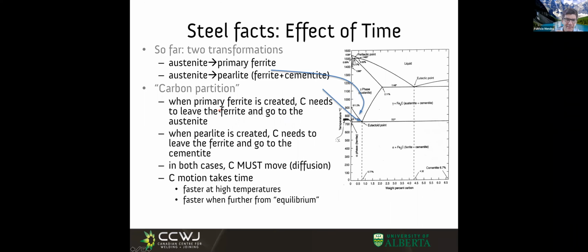So that takes time. And when the pearlite is being created, the carbon needs to get out of the austenite, so the austenite can turn into ferrite, and then that carbon needs to go into the cementite lamella. So right there, you can imagine, because there is this diffusion happening, if I have a very coarse pearlite, I have a long diffusion path, and it takes long to do. If I have a fine pearlite, I have a short diffusion path, and that can happen faster.